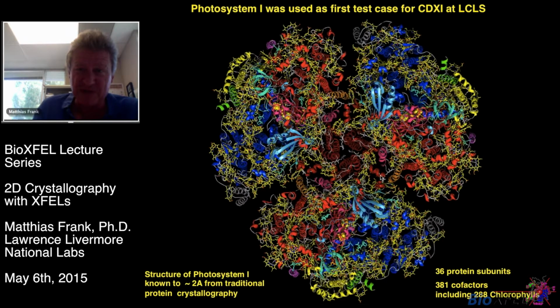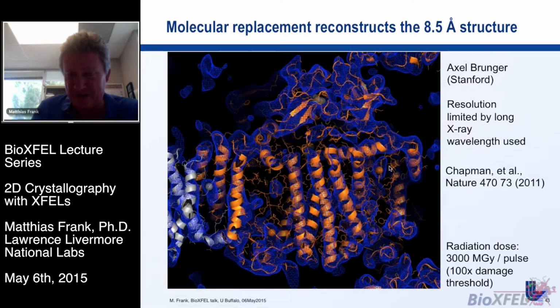Photosystem 1 was used as a first test case. It's somewhat counterintuitive. It's a very large protein complex, but it's one that actually forms crystals. It's a membrane protein that can't be crystallized easily. And so instead of using some small protein crystals, people were going for large molecules right away and just basically trying it. The structure was known from traditional crystallography, so it was a good test case. And in these first experiments, the structure could be reconstructed to about 8 angstrom resolution, which was commensurate with the X-ray photon energy that was available then, which was only 2 keV.